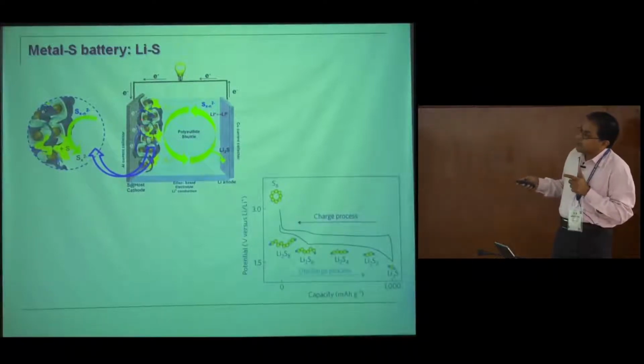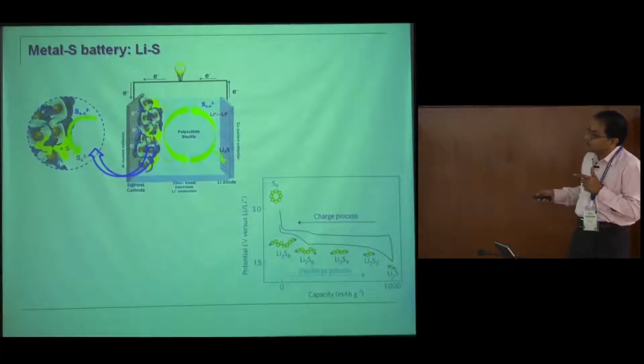But the problem with sulfur chemistry is, when you charge-discharge a battery, it goes through a large number of various polysulfides. Some of them are actually soluble in the liquid solutions that are used as electrolyte in the system. So the problems are, again, plenty. It's a tackleable problem. You could have anode poisoning, the final product forming on the anode side rather than on the cathode side. You could have volume expansion, and then of course you have to handle the insulating nature of sulfur and the polysulfides which are formed during the charge and discharge.